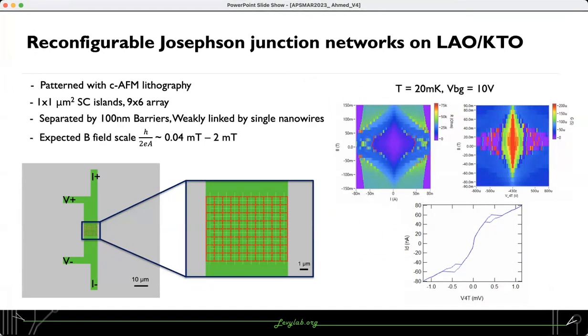The advantage here is that we can avoid the lift-off procedure, and there is no chance for a barrier to occur. The data from the first device shows very interesting behavior with lots of fine structure that requires much slower magnetic field sweeping than was feasible during this experiment. But it's quite sufficient to show that it's possible to create Josephson junction arrays. We are interested in investigating some of the outstanding questions about the 2D metal phase in between the insulating and the superconducting phase. This can be achieved by backgating the same device to operate in the different regimes.